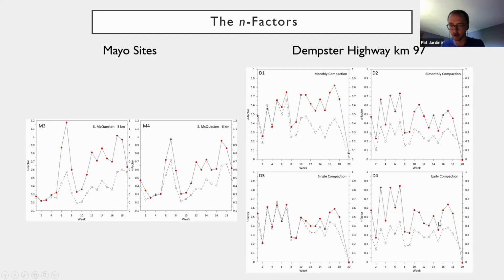Surprisingly, the undisturbed snowpack in Mayo had a larger N factor than the undisturbed snowpack of the Dempster Highway site, even though the density was much lower. And in general, the effects of compaction thermally were very similar between sites. Both were able to replicate the effects of a thin snowpack by pushing the N factor up towards the higher end of what's found naturally.